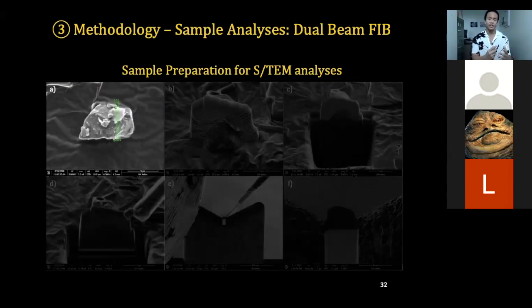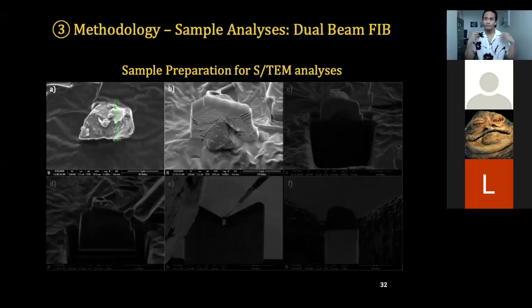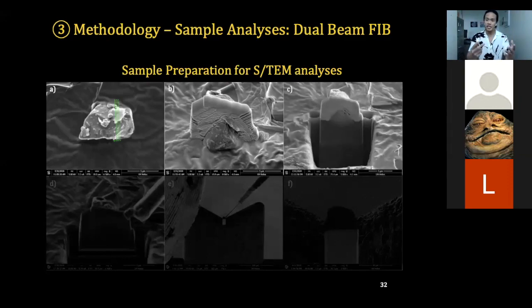Once we have a desired region, we then deposit platinum on top of that green rectangle, as you can see in image B. And this platinum will act as a shield and a protective barrier for when we are cutting both sides of our particle. Image C shows both sides of the particle being milled or cut. And as you can see, the platinum is still there protecting our desired region.